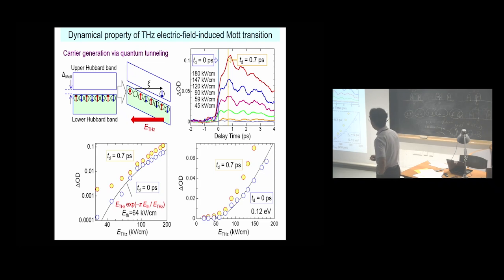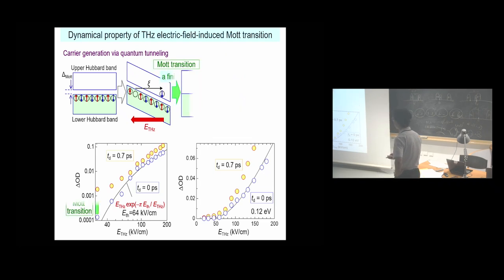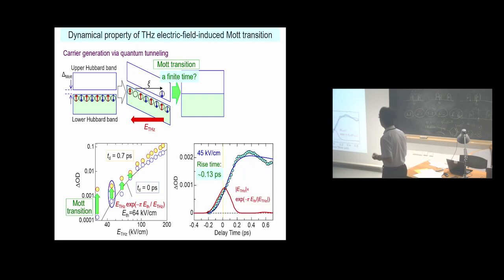So this is a logarithmic plot, and in the weak electric field region, the Mott transition seems to take a finite time. To clarify this feature, we analyzed the time evolutions of the absorption changes at this electric field and evaluated the rise time to be 0.13 picosecond. You can consider this rise time a characteristic time of the Mott transition.